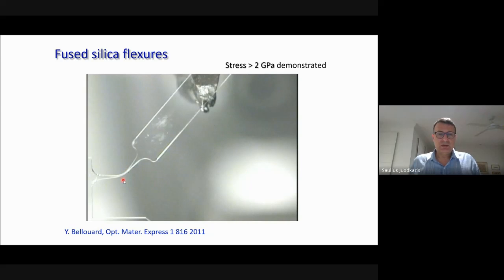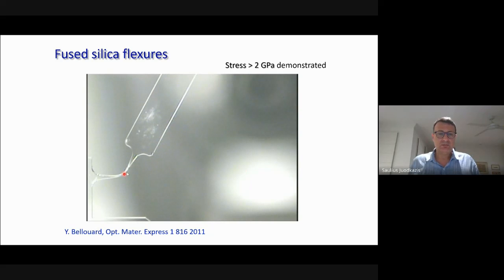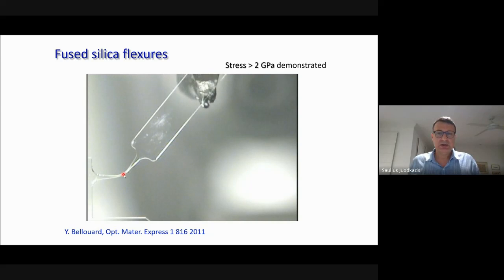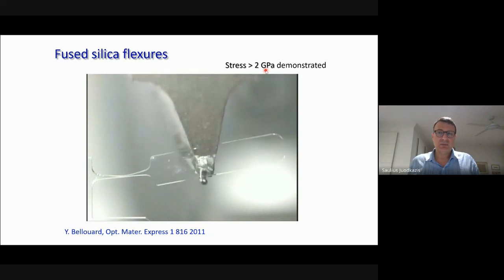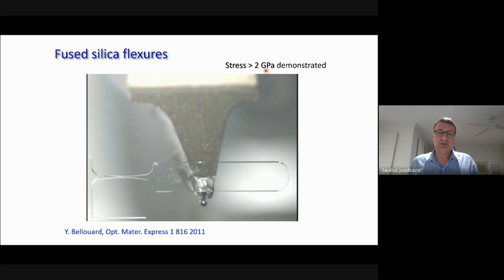So the stress in this region is reaching 2 gigapascal. It's basically the limit for glass. And glass is not breaking because all this glass was cut by writing femtosecond laser damage and then putting it in etching solution. Etching solution was removing all stresses, all cracks. So to speak, it healed the glass. There were no mechanical failure points.